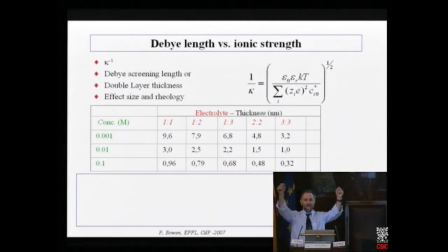The repulsive force is felt when these double layers overlap. Okay, so it's not like in your undergraduate physics lessons. The electrostatic repulsion is not the same as between point charges in a vacuum. Okay, this repulsion is because of the overlap of these layers. The composition and extent of the layer depends on the surface potential of your material.